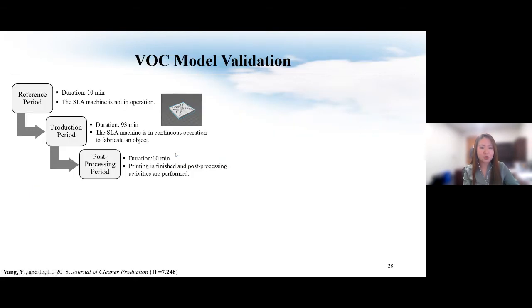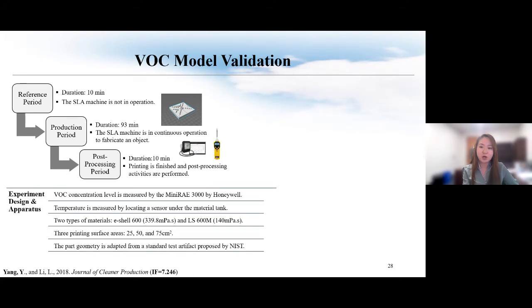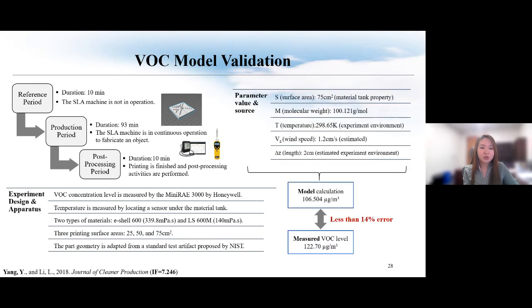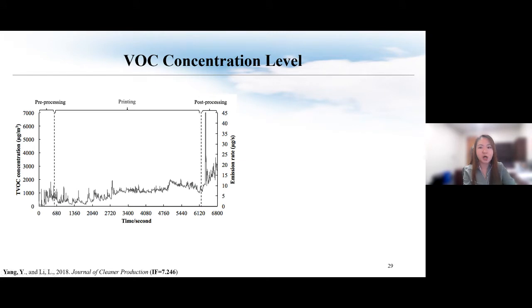We validated this model through experiments using a real-time VOC monitor. We did multiple experiments for different materials, for different production scales to validate our model. And the model turns out to have around 14% error. Next, let's look at one of the experiments. I want to show you this plot. The vertical axis is VOC concentration, the emission level. The horizontal axis is time. Based on time, we divided the entire experiment into 3 stages. The first one, pre-processing stage, where we were just setting up the machine, preparing for the printing. The second stage is the actual printing, where the machine fabricates a part.